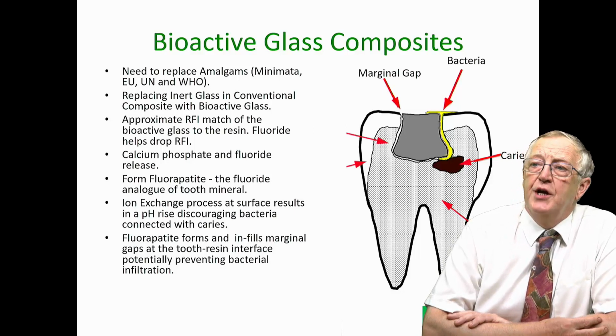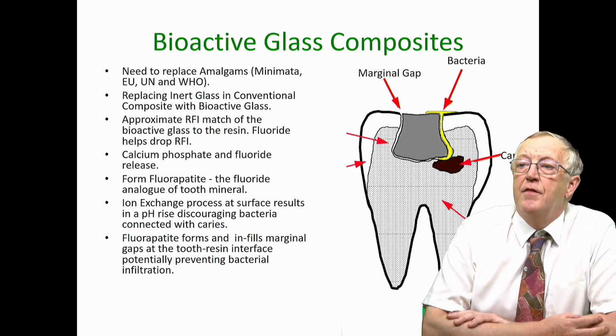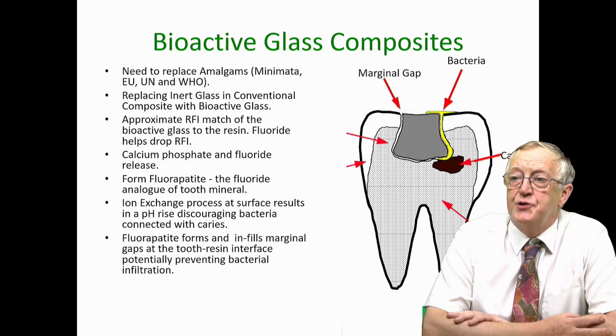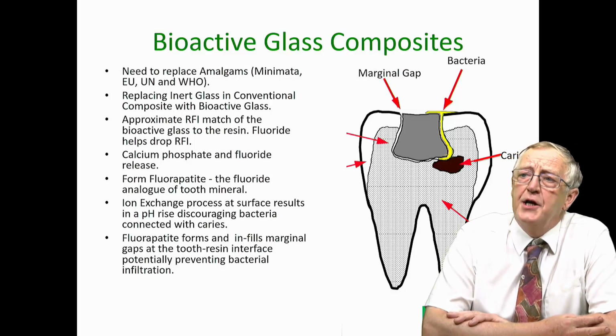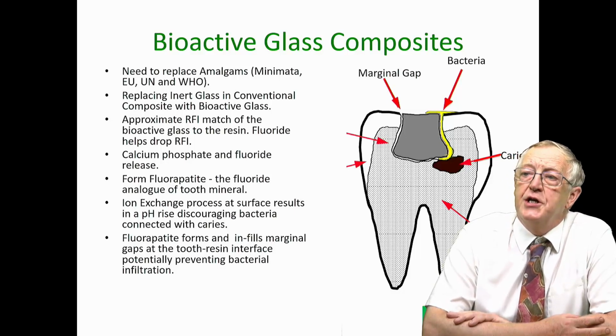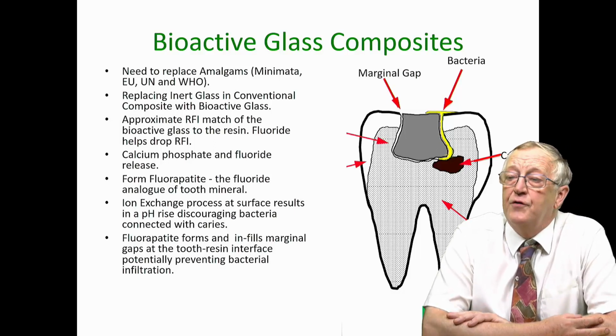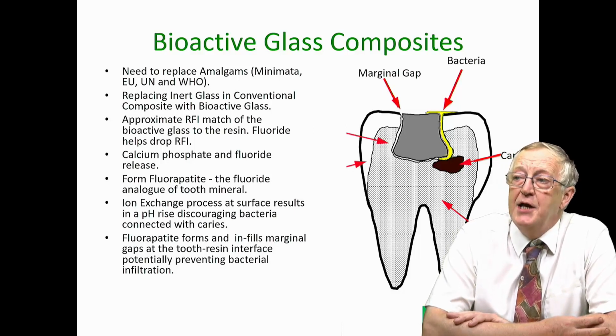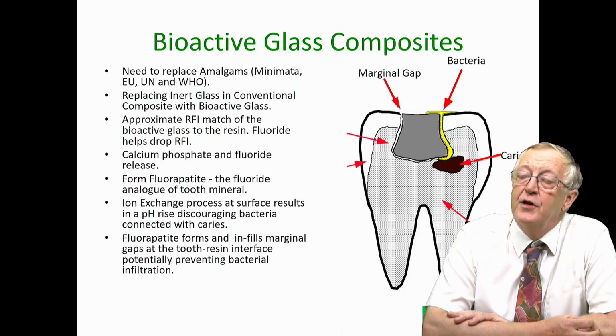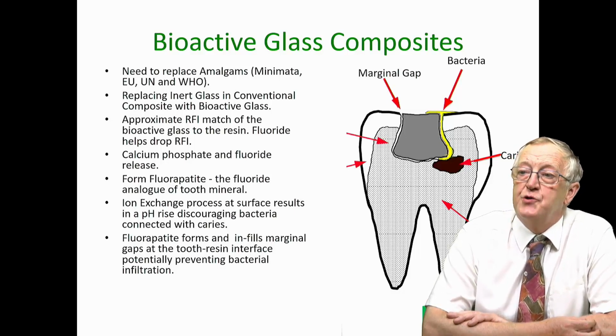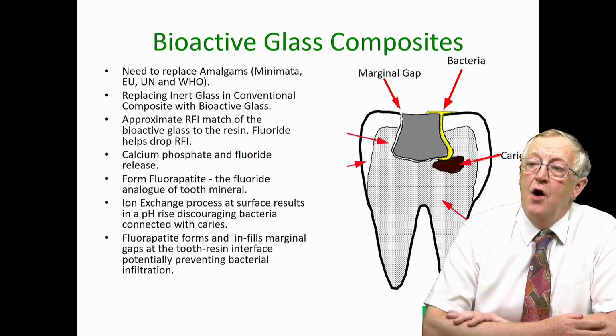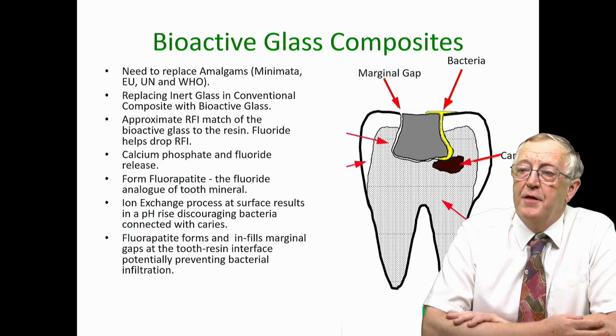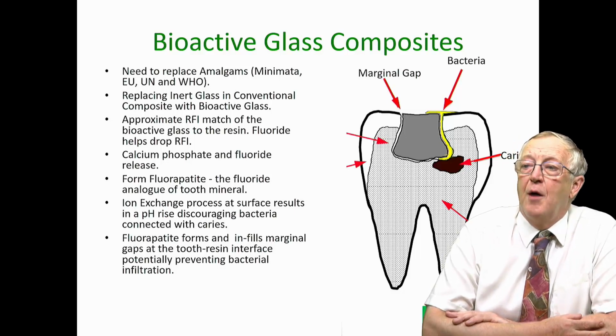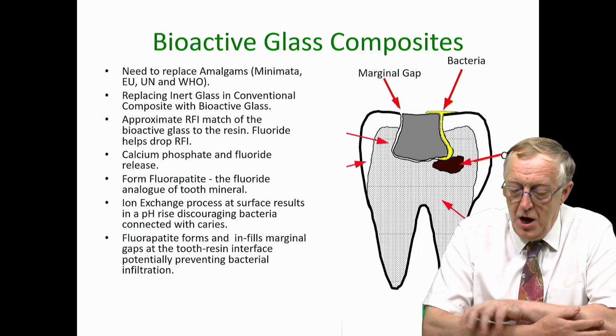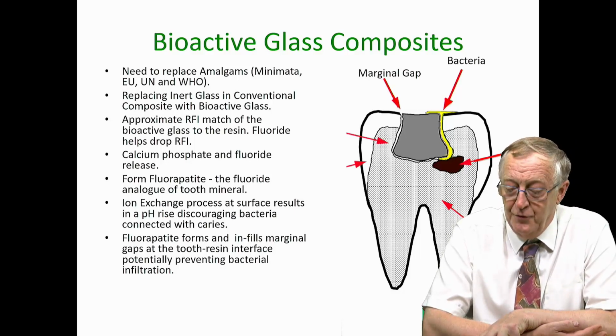These new bioactive composites release calcium, phosphate and fluoride. They form fluorapatite as the toothpaste does. And more importantly, the ion exchange process at the surface, particularly in the marginal gaps, results in a pH rise. And the bacteria involved in caries like an acidic pH. So the increase in pH towards 7 discourages many of the bacteria associated with caries. But also, over time, we infill the marginal gap with crystals of fluorapatite, which tends to seal the gap and prevent bacterial infiltration.